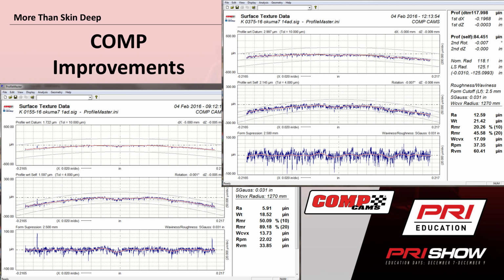What we find is, when we ground the first cam, we get this one on the left, and you can see it's running about 6 RA, about 50% RMR at 10. But by the time you've ground 40 camshafts between dresses, that wheel has broken down, and you're getting back from 50% toward 20%. And I'm showing Scooter this, like, we can get a good dress, but it's hard to hold a good dress. Now, we still got excellent contour.